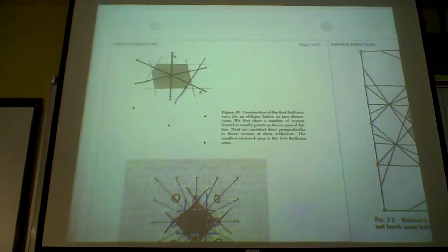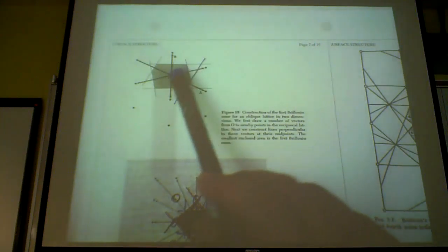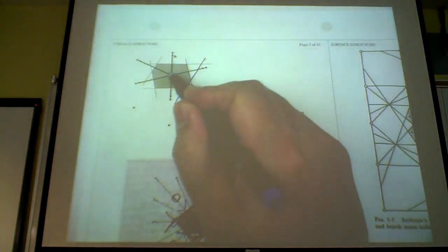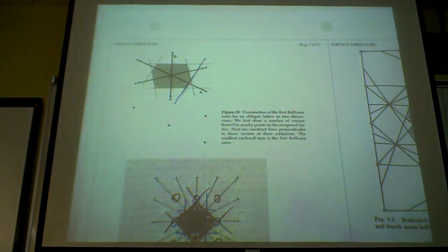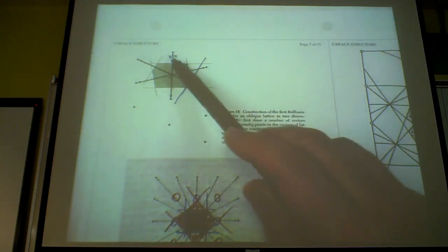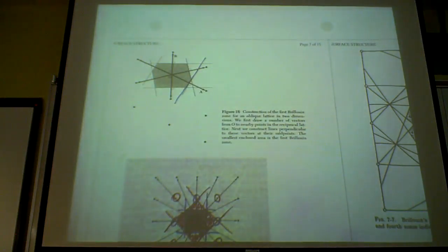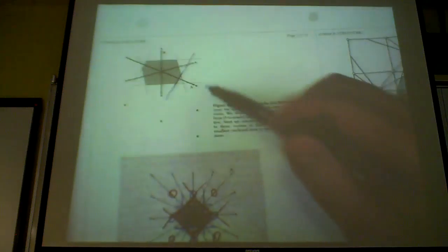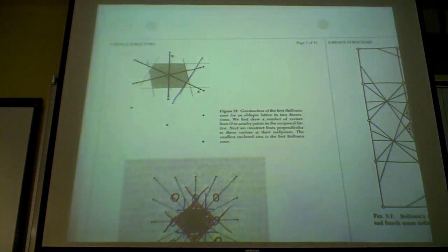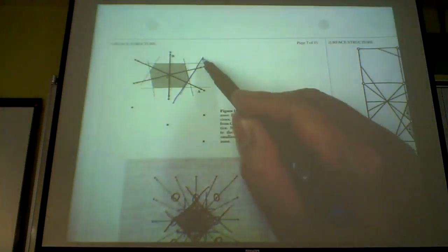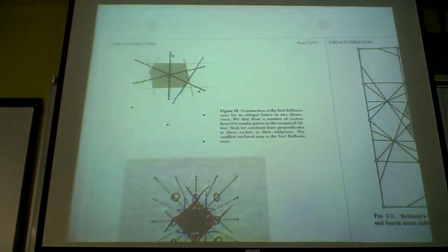Now a Brillouin zone is very simple. You pick any point, okay? So you pick this one here, and you connect this point to your nearest neighbors. I connect this to this, this to this, this to this, so all my nearest neighbor points. Then I take half of the spacing and put a plane across here. So this is known as the perpendicular bisector, along this length.